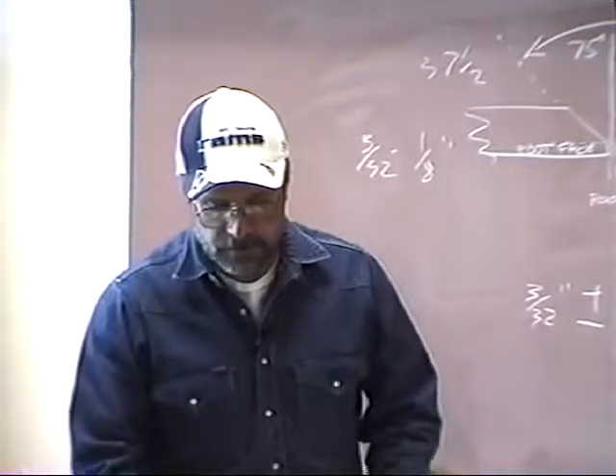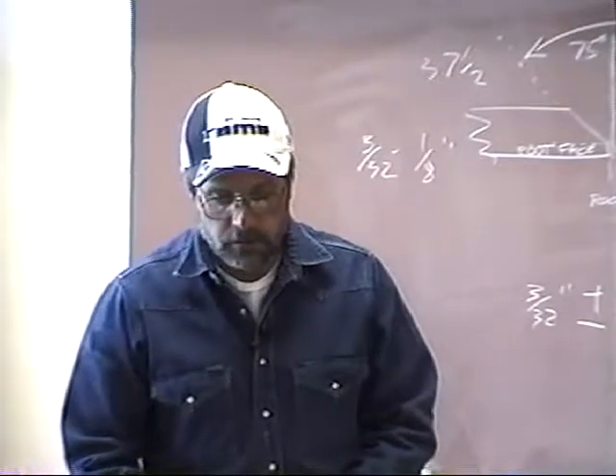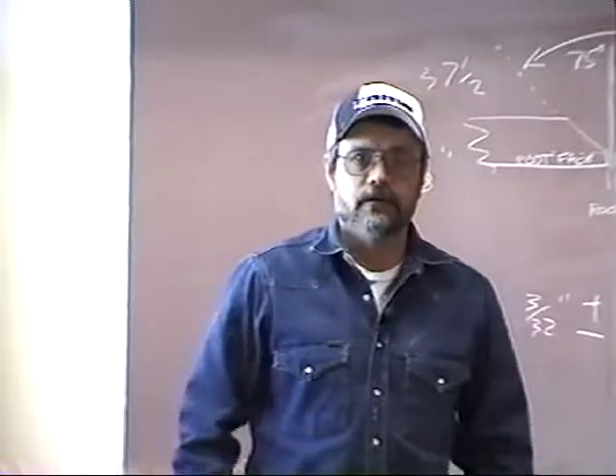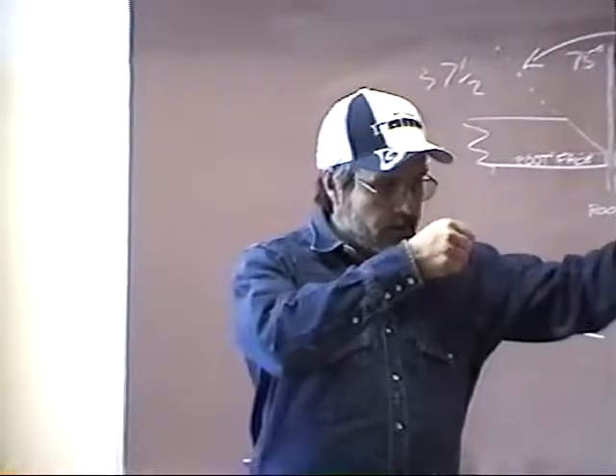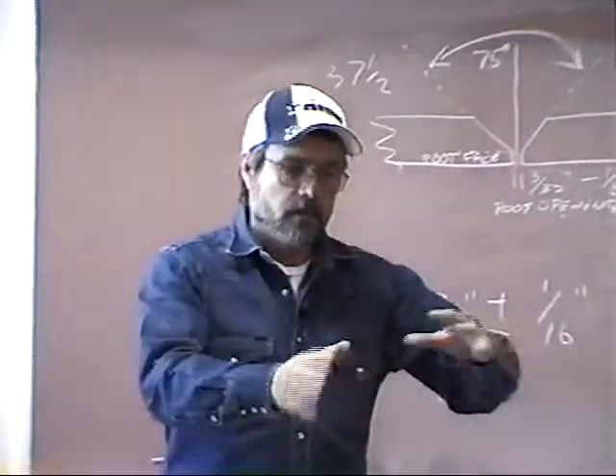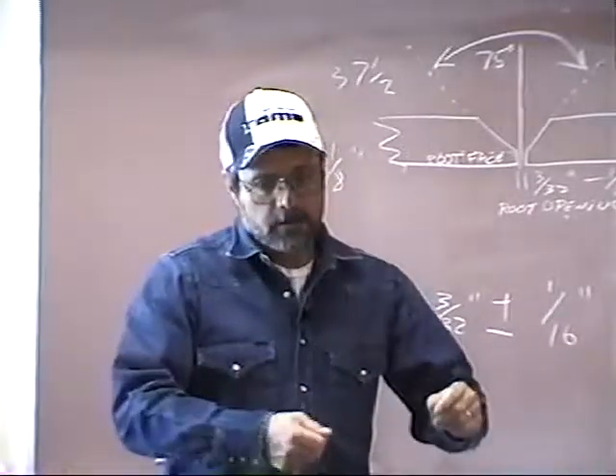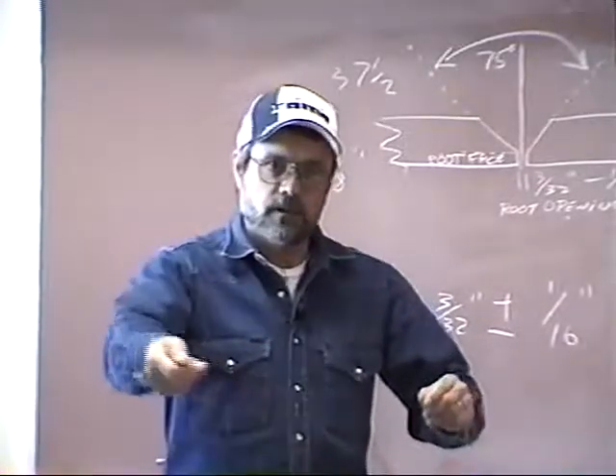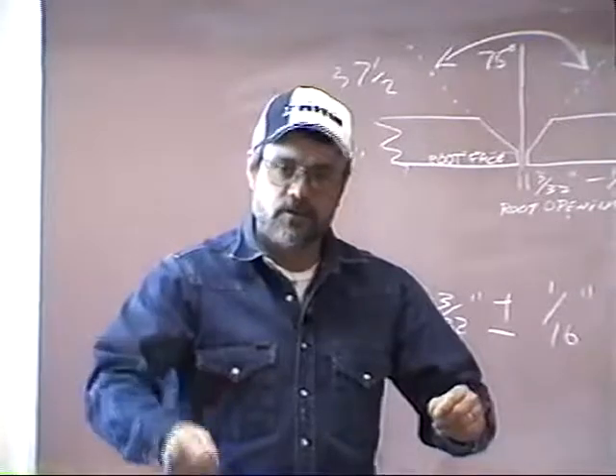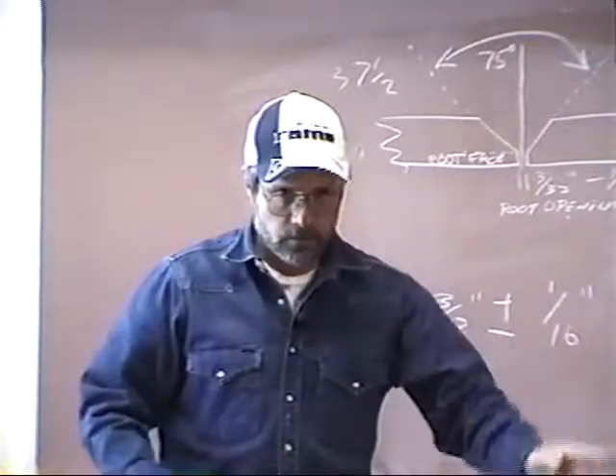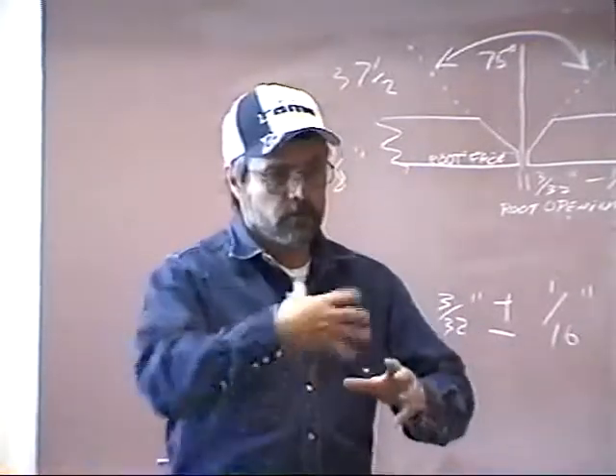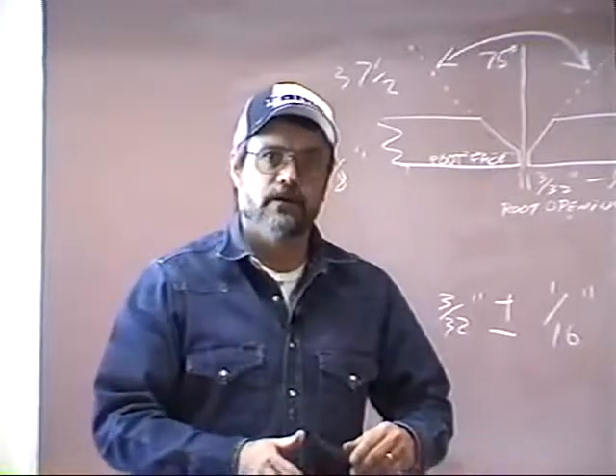Hand-cut pipe beveling machines like this are used almost exclusively in the field. It's a saddle-type machine. You simply put it on top of the pipe, adjust your torch, and you work it back and forth and turn on your cutting air, and then you just slowly crank it around, and it will burn that pipe off, and it'll just fall off, and you'll have a nice smooth bevel on there.